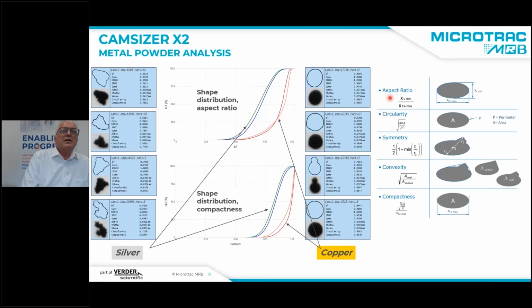Well, we can, for example, look at the aspect ratio, which is shown here in the first graph, which is the ratio of the smallest diameter, xc min, divided by the largest Feret diameter, for example. If this is almost 1, we have a spherical particle, and this is shown here for the copper, where we are really about 1 with this aspect ratio, while for the fringed silver particles we get values around 0.6. Another value could be compactness, and again a value of about 1 shows us that we are dealing with spherical particles, like this for copper, and values much less than 1 show us non-spherical particles, as we have here for silver. So with the help of image analysis and the shape factors, we can get much better information about our materials.